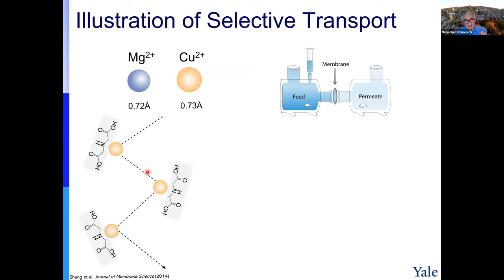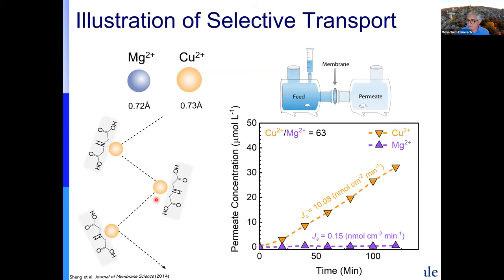This is the membrane with the diamino acetate. And indeed, we were able to reproduce the idea of the potassium channel. You see the permeate concentration. We get high flux of copper because copper can bind to these groups and then hop and jump the way of the potassium channel. And for magnesium, the log stability constant is about 2 compared to 10, so it doesn't have this ability and doesn't go through the membrane very effectively. So we were able to achieve a selectivity of 63, and we extended it to different metals and were able to show a lot of interesting things.